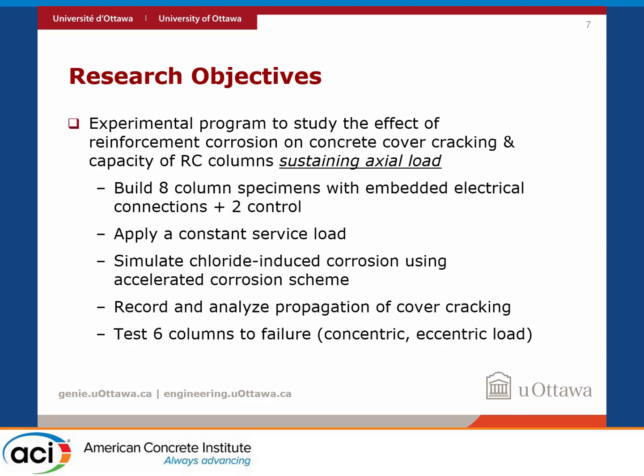We simulated the corrosion process using an accelerated corrosion scheme. We monitored the crack propagation and measured crack widths. And then at the end of the period, when we reached the level of damage that we wanted to obtain, we tested 6 of those corroded columns plus the control ones to failure. Some of them were under concentric load and some had a little bit of eccentricity, sustaining a little bit of bending moment as well.